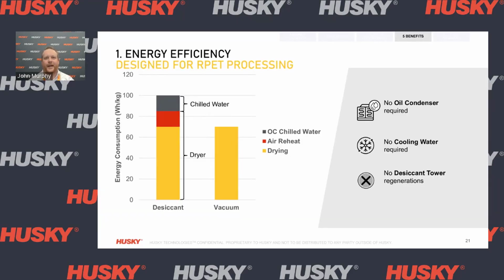Now I would like to present the main topic of today's webinar, the 5 benefits that a vacuum drying system can provide when processing rPET material. The first benefit is energy efficiency. For processing virgin material, a desiccant drying system and a vacuum drying system are very similar in energy consumption, at around 70 watt-hours per kilogram in the best case scenario. Once we start looking at processing rPET material, we see a significant benefit in energy consumption for the vacuum dryer.